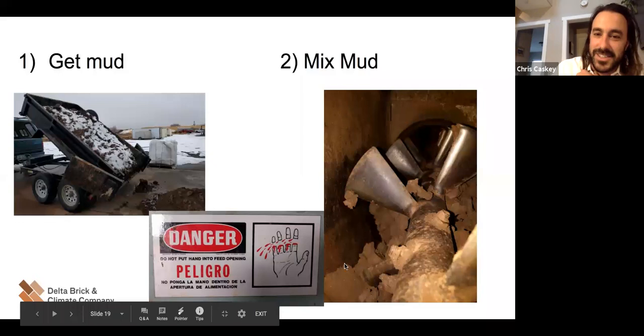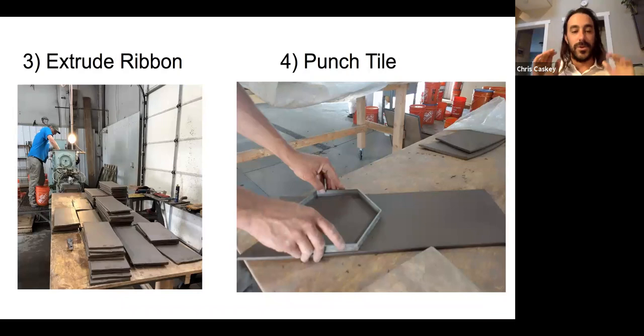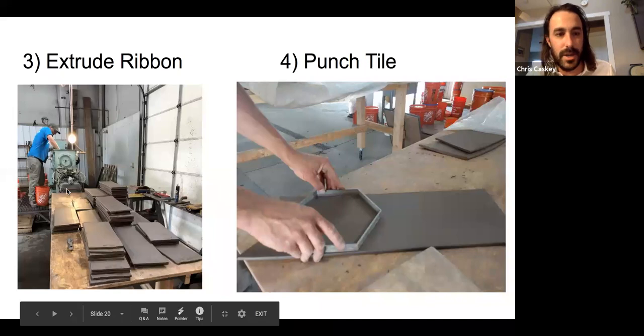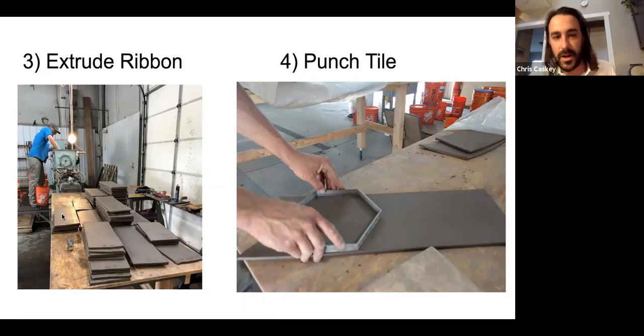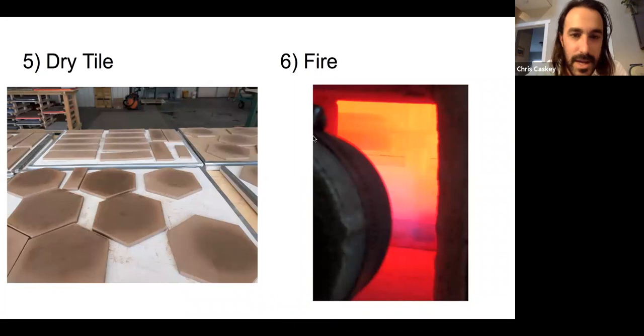And then you extrude. What we have is a machine called an extruder, which is a big auger screw, and it just pushes the mud out of whatever opening we put on the end of it. In this case, it's a thin rectangular opening, which pushes out a lot of ribbon. We then straight up use a cookie cutter to punch that ribbon into whatever shape we want. We then dry that tile, fire that tile.